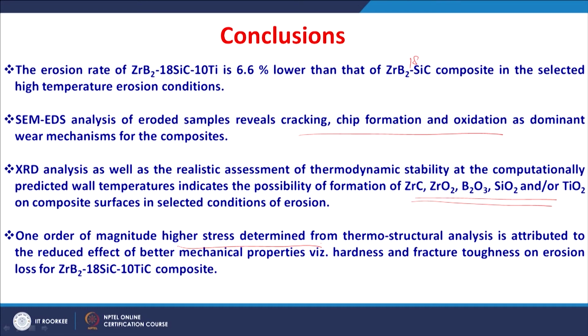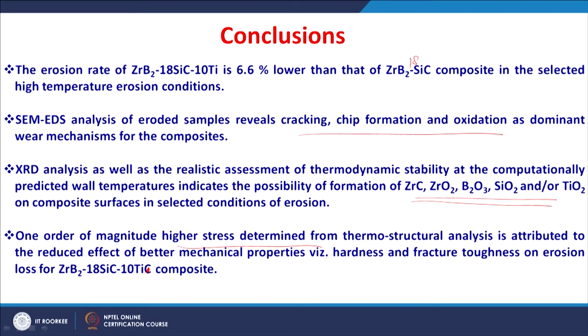So, these higher stresses are attributed to the reduced effect of better mechanical properties like hardness and fracture toughness on the erosion loss for zirconium diboride silicon carbide titanium composite. So, in spite of having large improvement in the hardness and fracture toughness, there was less improvement in the erosion wear resistance for the zirconium diboride silicon carbide titanium composite compared to zirconium diboride silicon carbide. So, this discrepancy can be understood only by this computational analysis that we did using the finite element model.